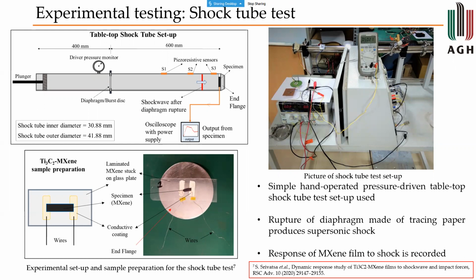This is a classic shock tube experiment that we performed. Probably I've shown this in the Divert project multiple times. But one of the reasons that we use this as a standard experiment is most people in the industry, when they develop sensors, particularly pressure sensors, use this as a test setup so that you have repeatable impact of forces on the sample. So the rupture of the diaphragm in the tube would actually release a shock wave which